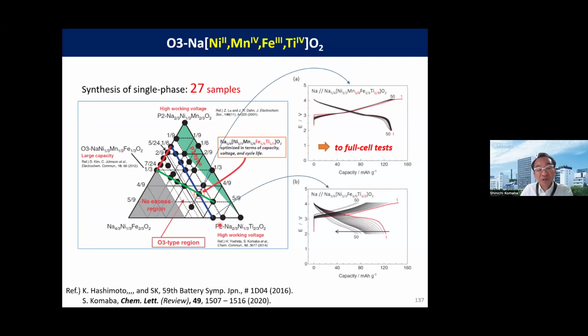In the next plot, this manganese-free composition is surprisingly bad. Very, very fast discharge capacity decay. So compositional optimization is very effective. And recently we are trying to apply a data-driven computational study to find new materials based on the nickel manganese iron titanium system. Anyway, based on this optimization, we tried to assemble a full cell.